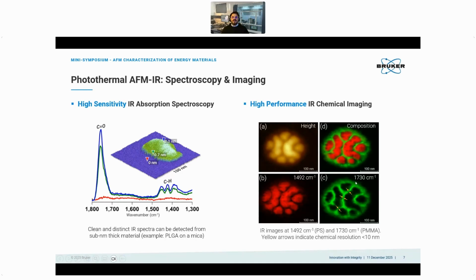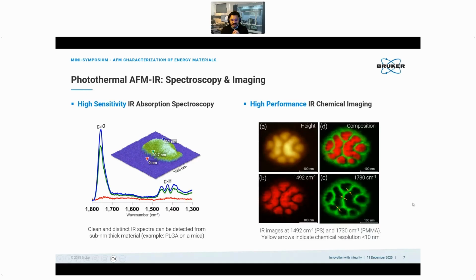And at each position, the wave number of the infrared laser will be swept, and the amplitude of absorption will be collected, creating these local spectra. Now, what's interesting is, see, for example, this 3D representation here, the scan size here is 100 by 100 nanometers. So now when we speak about spectroscopy, right, we're speaking about nano-localized spectroscopy, which basically allows you, if you already do normal infrared spectroscopy, to gain hugely in terms of spatial resolution and discriminate between local changes on your materials, something that you will see weighted, or let's say averaged, with a normal infrared.